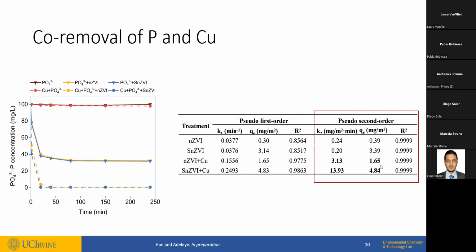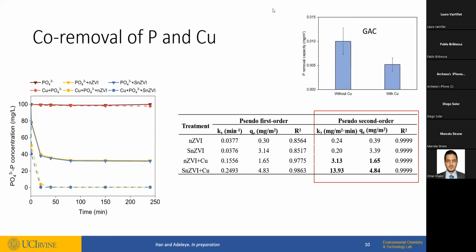And if you want to get what I mean by really high, so here's a plot that shows the capacity of GAC for phosphate with and without copper. So with copper, the capacity is 0.005 milligram per meter square of the surface of GAC, but you can see that with the 2 nanoparticles, we are talking about 2 to 3 orders magnitude higher in terms of removal. But this is for phosphate.